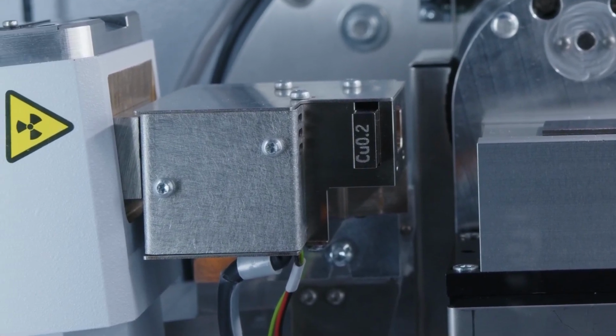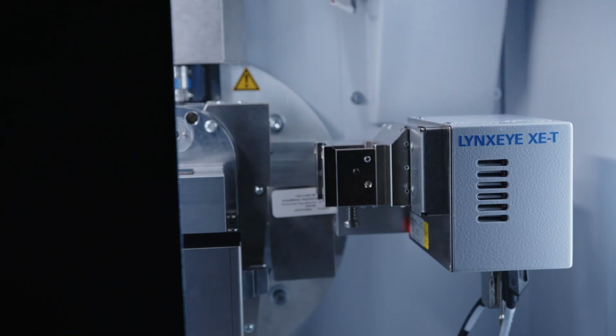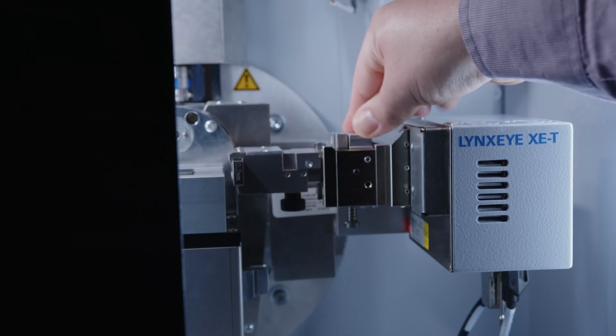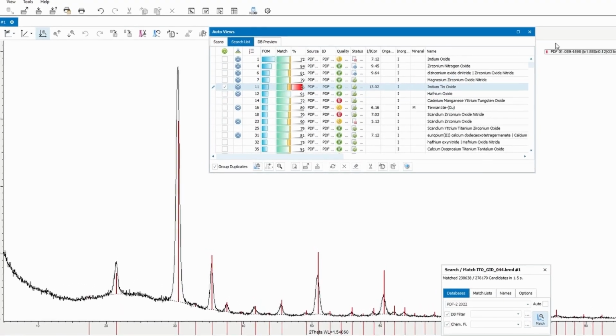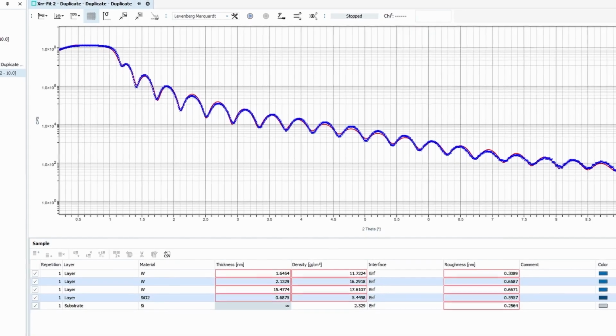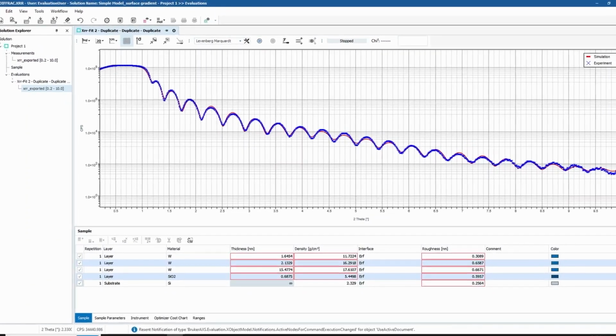Both of these techniques require the use of a thin parallel X-ray beam. In the D6 phaser, this is accomplished using the advanced primary optic. To further refine the beam condition, a secondary optic is placed in front of the detector. In the case of GID, a parallel equatorial soller, and for XRR, an extended slit attachment. Analysis for GID scans typically involves phase identification, which is performed in diffrac.eva, while analysis of reflectometry data is completed in DIFFRAC.XRR. Another advanced X-ray measurement that is enabled with a universal stage is residual stress analysis.